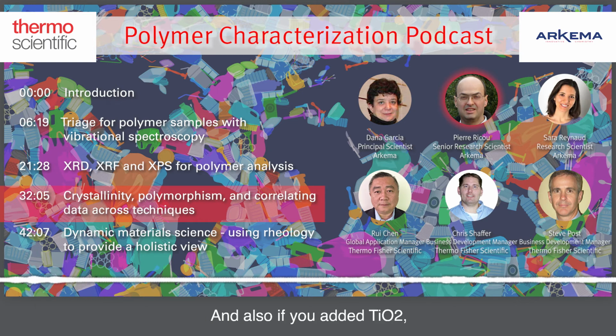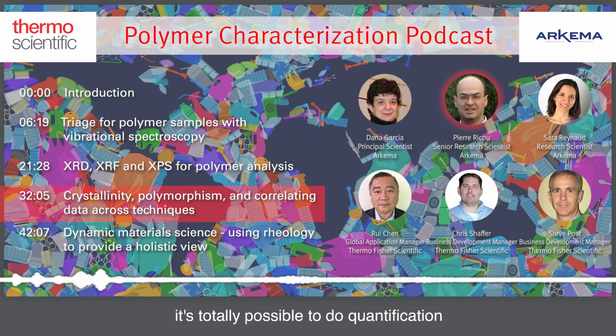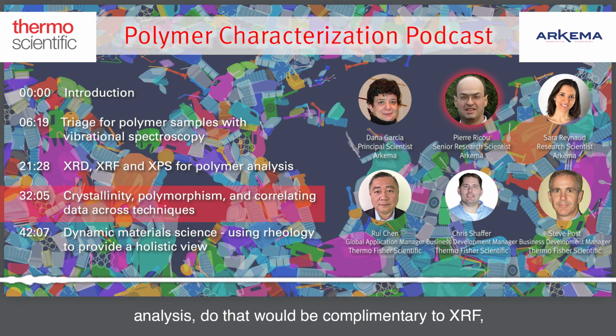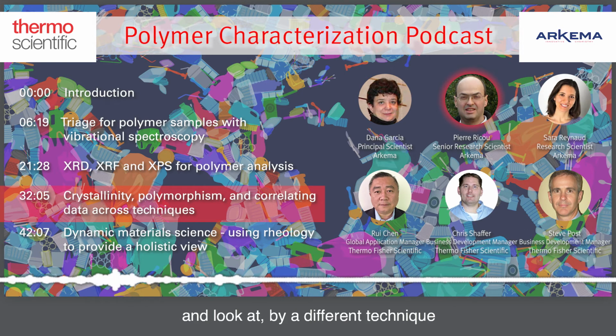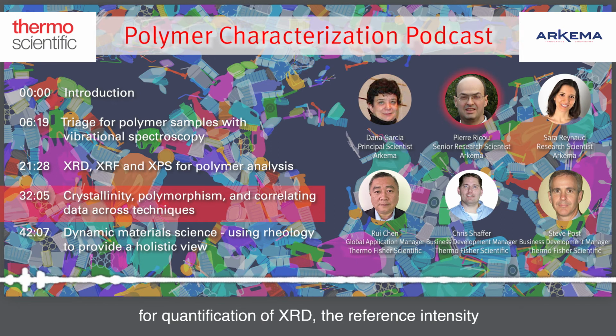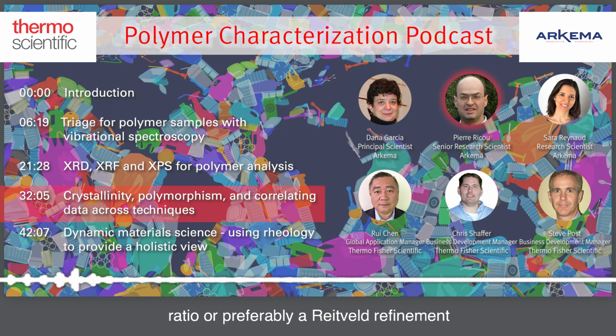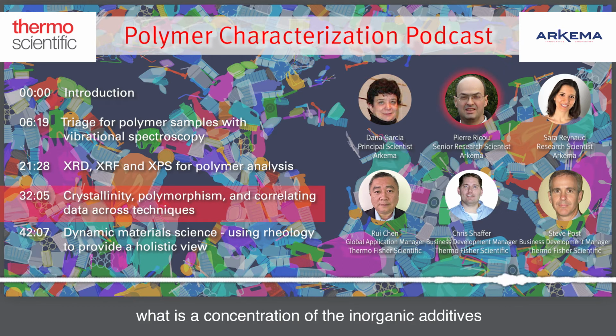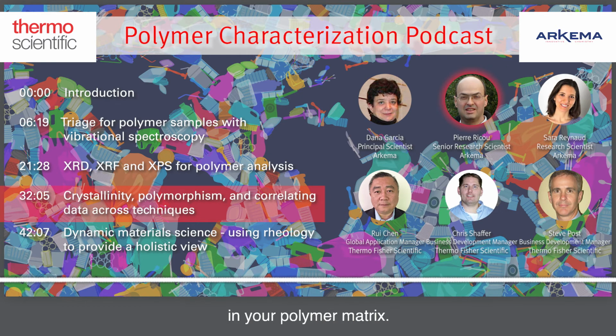And also, if you added TiO2, it's totally possible to do quantification analysis. So that would be complementary to XRF. And by a different technique for quantification, XRD, the reference intensity ratio, or preferably a Rietveld refinement, could also lead you to figure out what is the concentration of the inorganic additives in your polymer matrix. So those are kind of different examples.